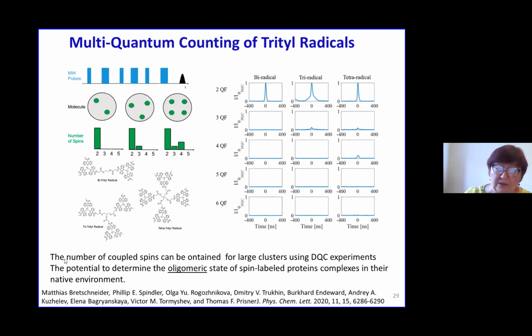Another work was initiated by Thomas Prisner. He would like to apply the methodology from NMR for studying multi-quantum counting of different radicals. That is quite well known in NMR, where they investigate different frequencies, 2 quantum, 3 quantum, and so on. Why is this interesting? Because in many cases biomolecules form aggregates, and then nobody knows which dipole-dipole interaction you are measuring. So one has to know if these aggregates are formed. In this case, it is a model compound. We would like to know if trityls can help in such cases.